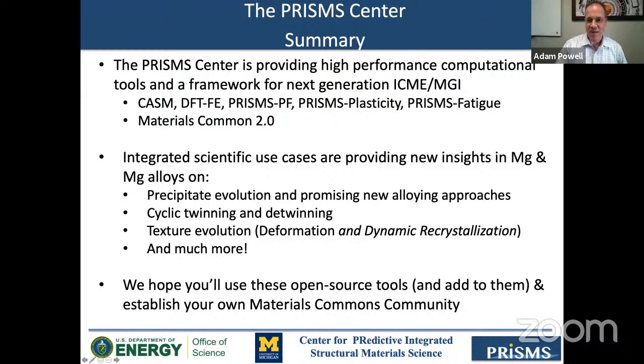Sure. So it's very interesting to see how there are different interactions between elements. You showed the example of calcium and zinc, and I wonder if there are others that you think are noteworthy, in terms of multiple elements where the individual elements don't have a particular effect, but combinations of them might? Well, certainly in the literature, calcium is a really important actor here. So calcium, in connection with many of the rare earths, have shown similar sorts of interactions.